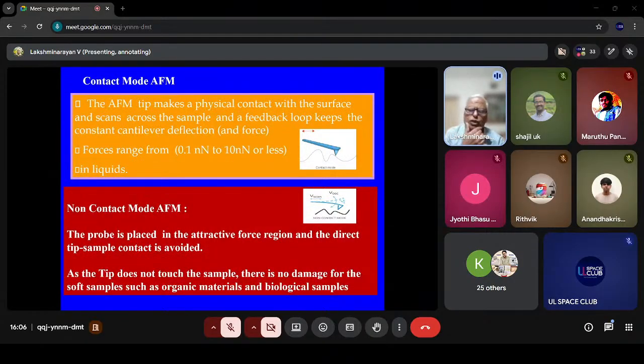To go into a little more detail about the AFM, there are three modes. One is called the contact mode, where the tip literally touches the sample. This is in the repulsive regime, with repulsive forces. Here it just touches the sample, and you keep the distance between the two constant, and then use the feedback. There's also something called non-contact mode. It doesn't really touch the sample, but moves just above the sample. It is mostly in the attractive regime of the Lennard-Jones curve.